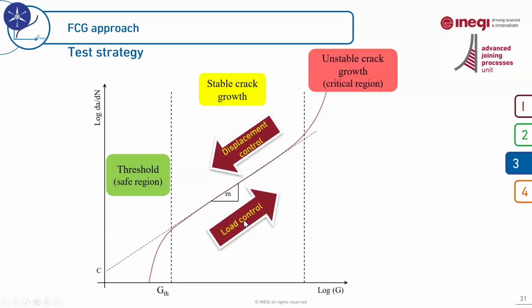In load control tests, usually we need to test several joints at different loading levels to be able to find a real threshold value. But in displacement control, only a single test can be enough to obtain the threshold.